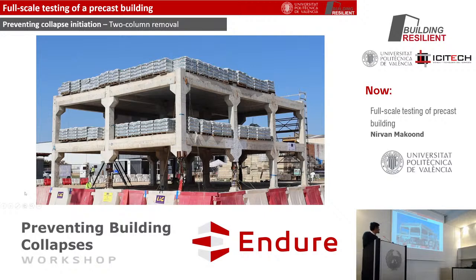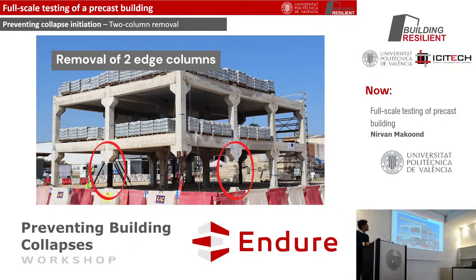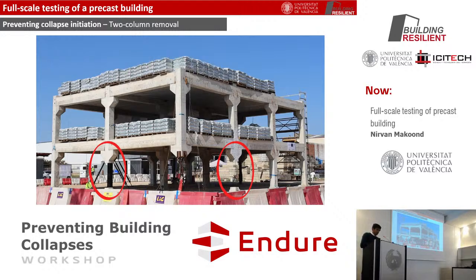Okay, so in this video we will see the first phase of testing, which involved the quasi-static removal of this column and this column gradually, and then the apparatus was pulled out to prepare for the second phase of testing. So here we will see one of the first columns has already been removed and the apparatus lowered. Now the hydraulic jack is being lowered from a distance, and this has already been pulled out. And as we can see, there's actually fairly small deflections. At this stage, the load was redistributed quite efficiently through the beams, columns, and slabs.